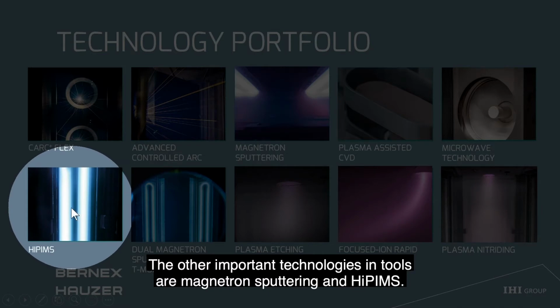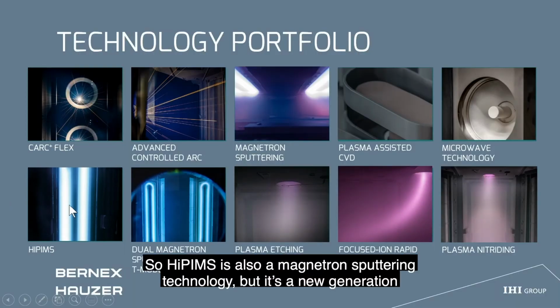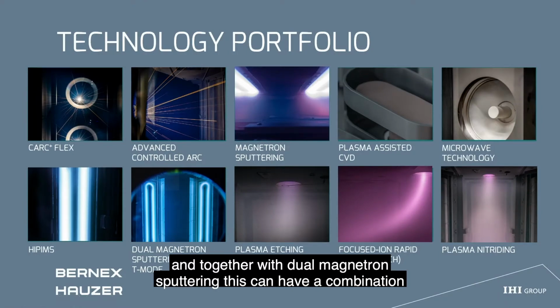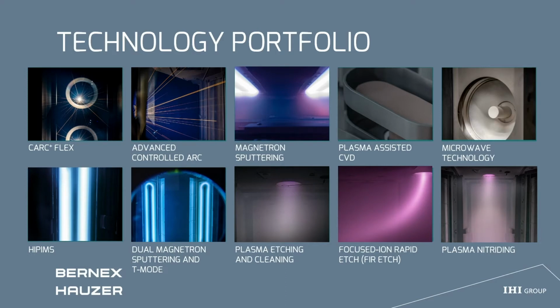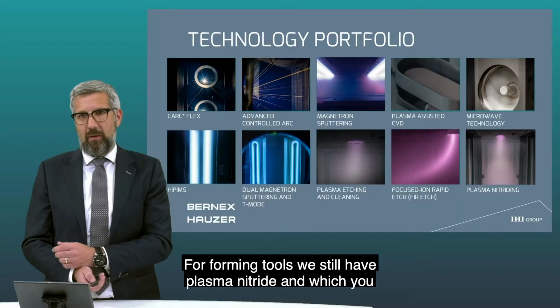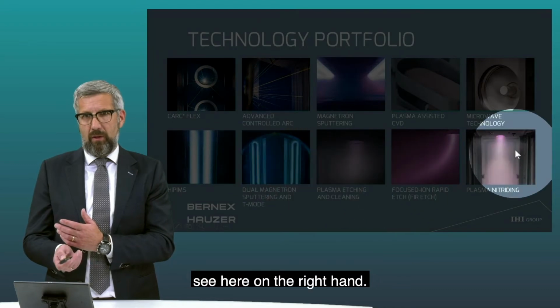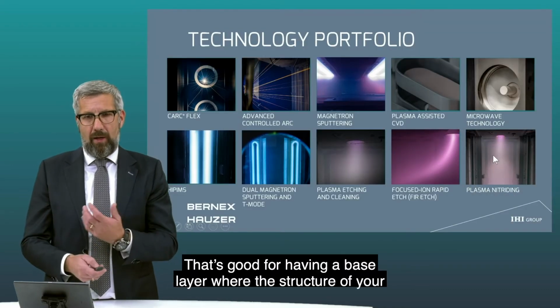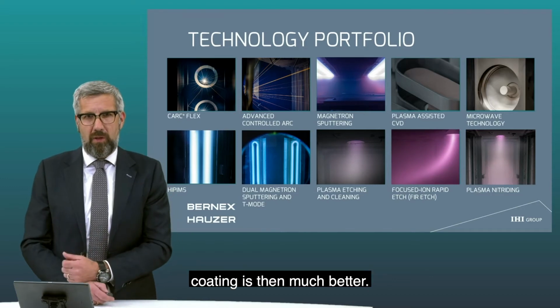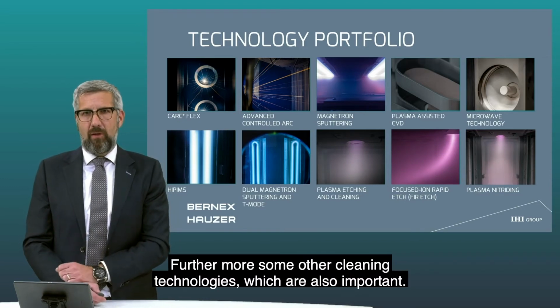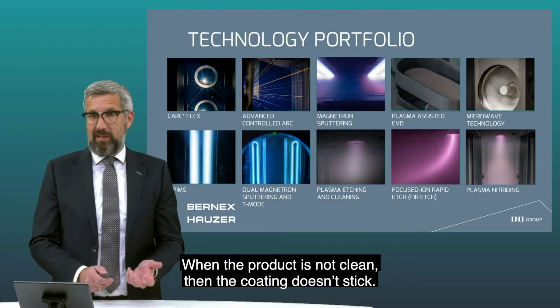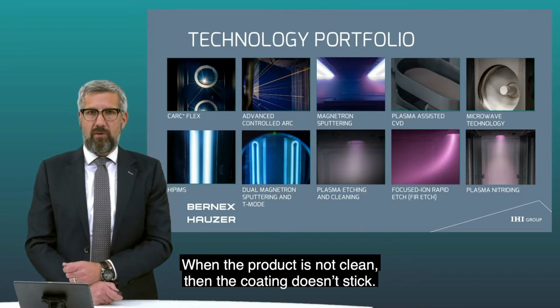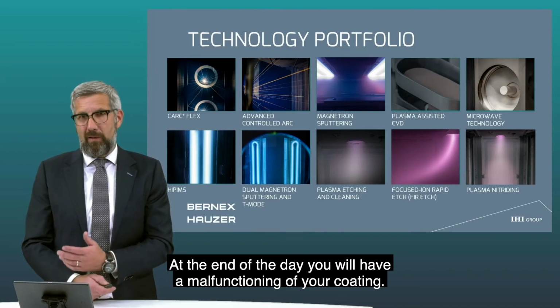So the other important things in tools are magnetron sputtering and, for instance, HiPIMS. So HiPIMS is also a magnetron sputter technology, but it's a new generation. And together with dual magnetron sputtering, this can have the combination of nitride coatings and oxide coatings. That's for the cutting tools. For forming tools, we still have plasma nitriding, and that you see here on the right hand. That's good for having a base layer where the structure of your coating is much better. Furthermore, there are some other cleaning technologies which are also important. If the product is not really clean, then the coating doesn't stick, and at the end of the day you will have a malfunctioning of your coating.